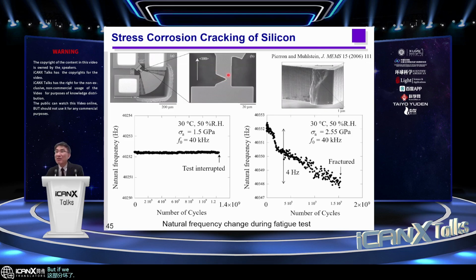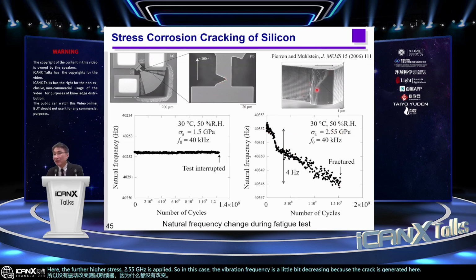But if it is made of silicon and tested at a certain condition, this MEMS structure doesn't break. So in this example, 1.5 gigapascal is applied here, and it is tested at room temperature, 50% relative humidity. So there are no vibration changes, and the test was interrupted because nothing changed. Here, a further higher stress, 2.55 gigapascal, is applied. In this case, the vibration frequency decreases a little bit because a crack is generated here, and finally the structure is fractured like this.